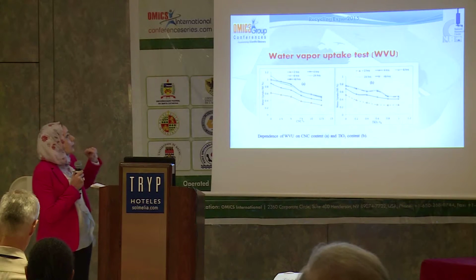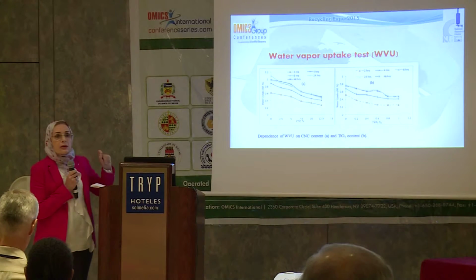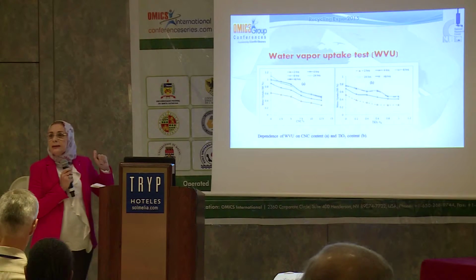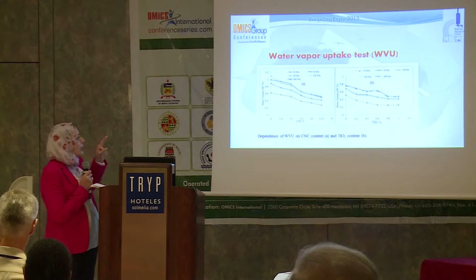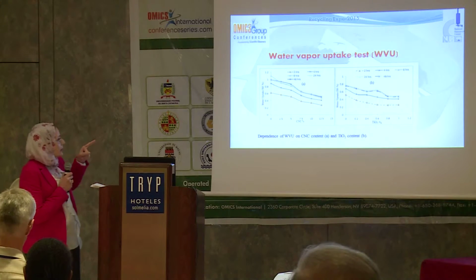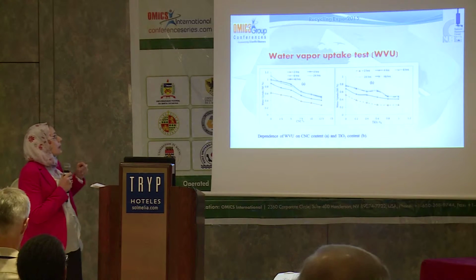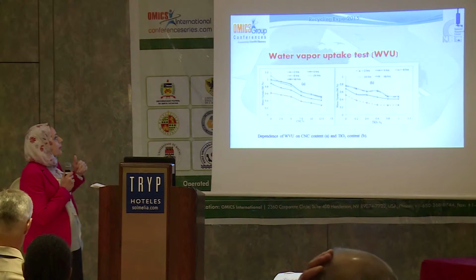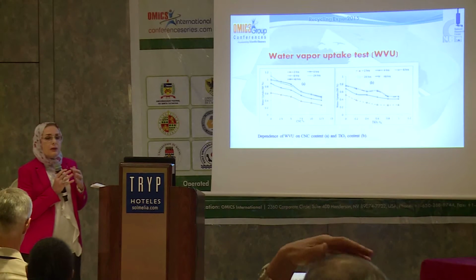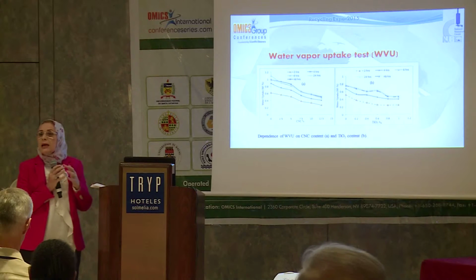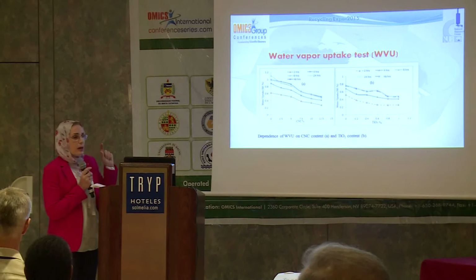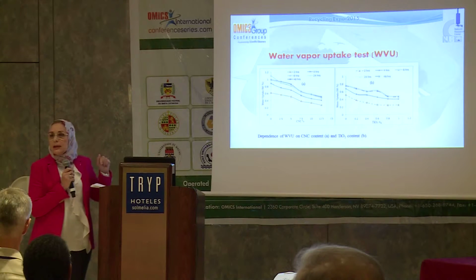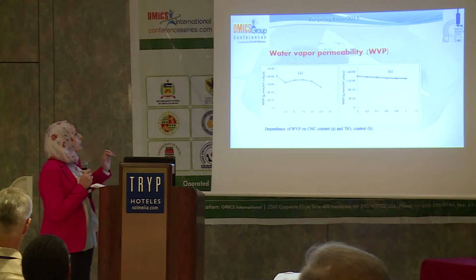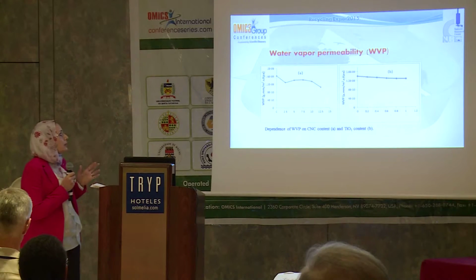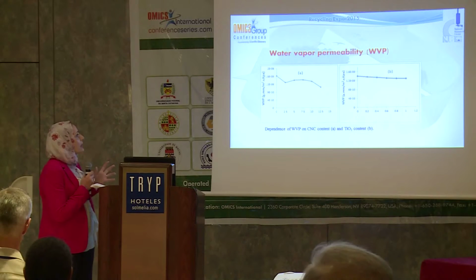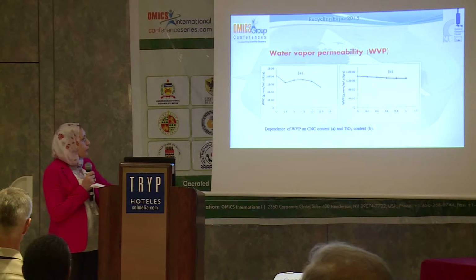Water vapor uptake was investigated under the worst conditions, under 98% relative humidity. We can see that filling with cellulose nanocrystals and titanium dioxide resulted in lower vapor uptake due to the network resulting from hydrogen bonding of cellulose nanocrystals and the amino groups constituting the chains in the protein. Also, water vapor permeability showed no significant enhancement, but it's less than the control.